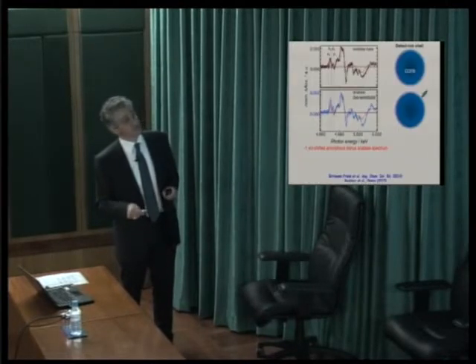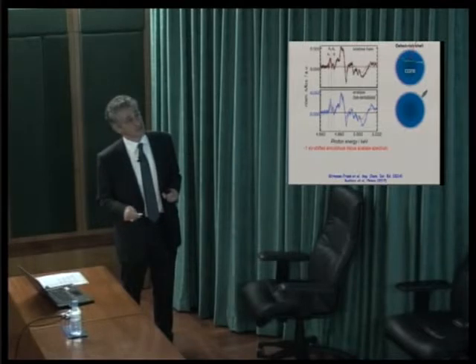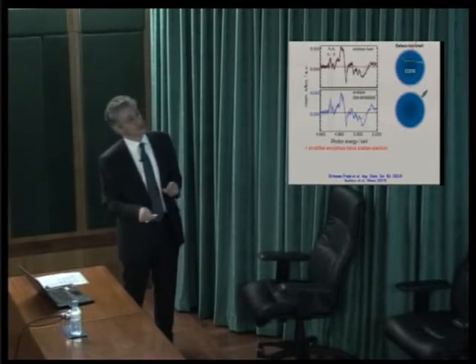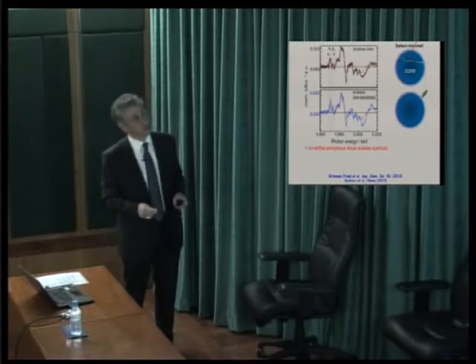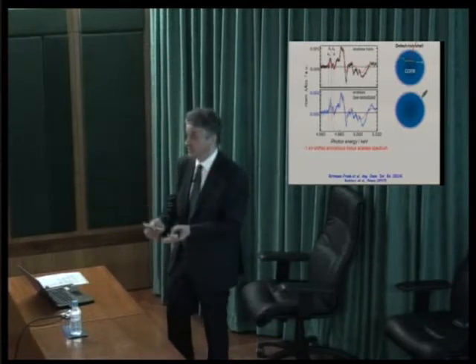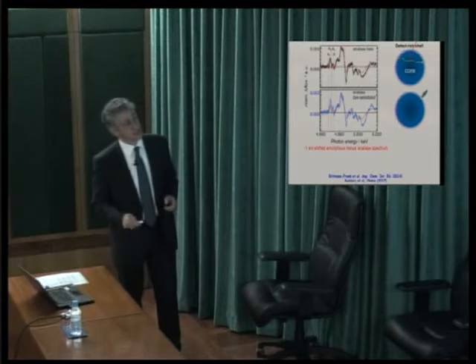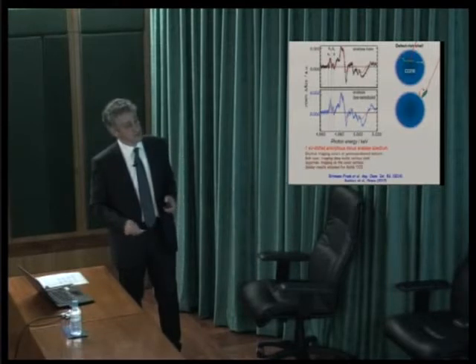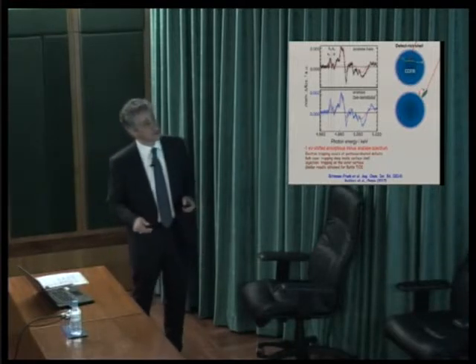So just to summarize these transients for the bare and the dye-sensitized, what happens here is that when you excite the bare nanoparticles, you create these electron hole charges that migrate and get trapped in the deep shell of the nanoparticles. These nanoparticles have defective shells and rather crystalline cores. And that's normal because it's a nanoparticle, so you have truncation effects, you have all sorts of things happening at the surface. And we could also interpret these data for the dye-sensitized in the fact that when you inject an electron from outside, then it gets really trapped on the outer surface. And we could even demonstrate that these are pentacoordinated defects. I mean, we analyzed all these data, actually. The red dashed curve is the analysis.